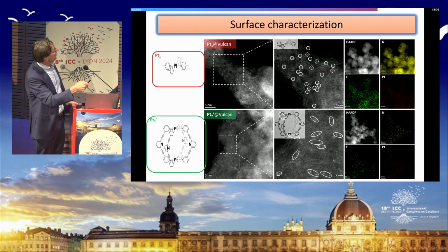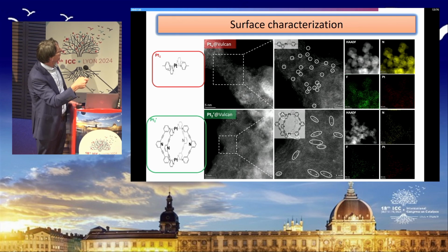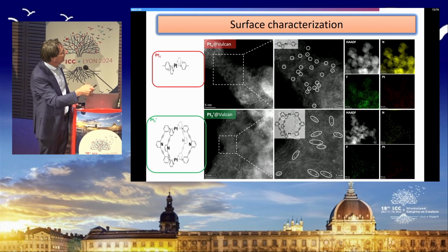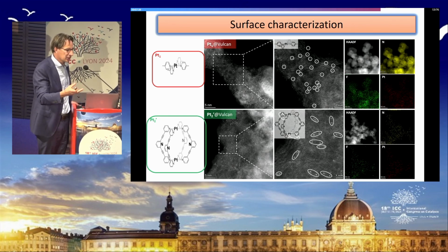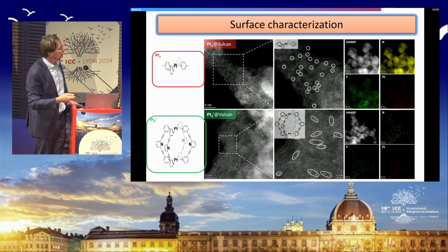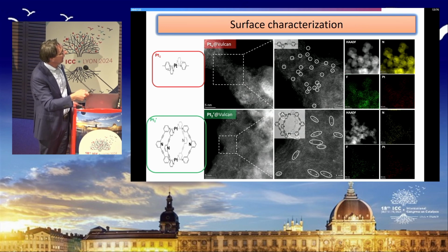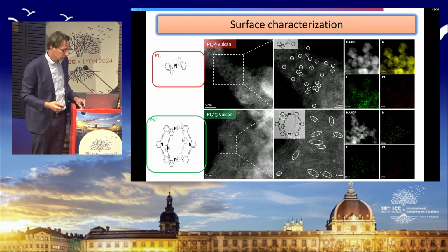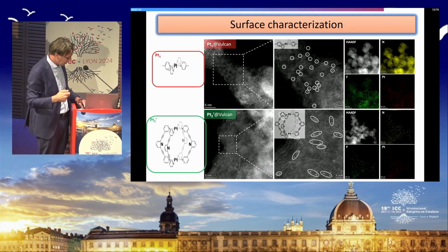So we analyzed the surface of this, and this is in collaboration obviously, we don't have electron microscopy. But here we compare the monometallic with the bimetallic, and all the dots here are single platinum atoms, and here too. And if you zoom in, here you see a random distribution of these platinum atoms, and here you see that the platinum atoms are always coming in pairs in line with the cage being adsorbed onto the Vulcan material. Also, we did HAADF. And here we established that if we have platinum, we also have fluor as the counterion and nitrogen based on these ligands. So all in line with surface grafted molecular complexes and molecular cages.